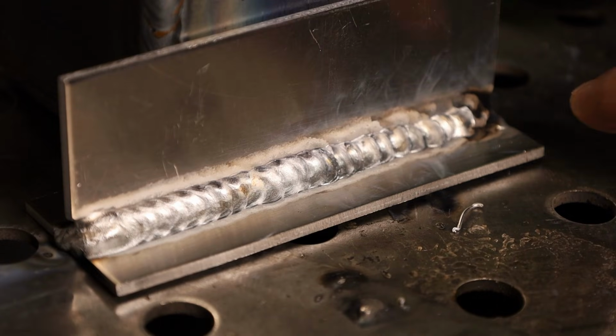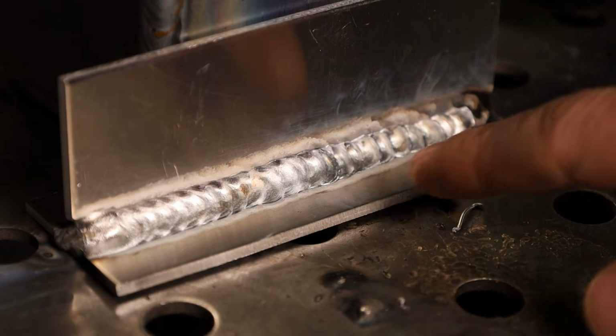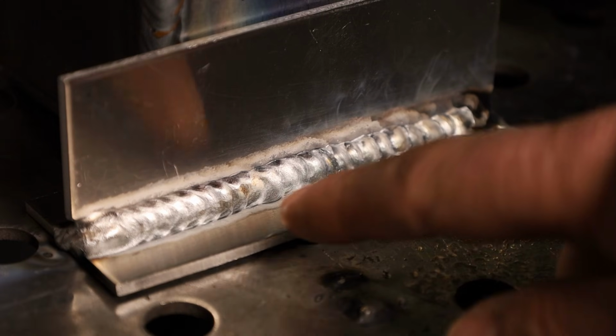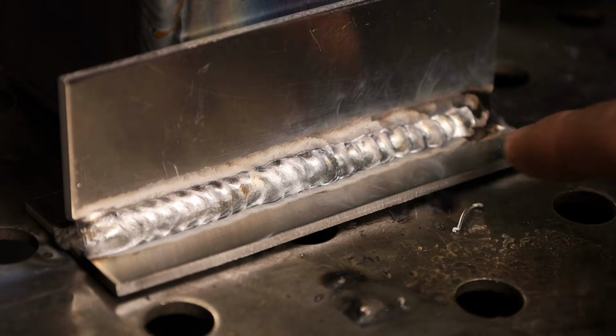Now here I'm getting a little bit of shorting out, short circuiting there at the start. So my voltage was just a hair low, but I think it's because of my stick out. So I moved in a little closer, and it's just subtle there, but you want a short stick out when you're MIG welding aluminum. But notice there at the start how it's sitting just a little bit more peaked on top versus the second half of the weld after I moved in on my stick out.